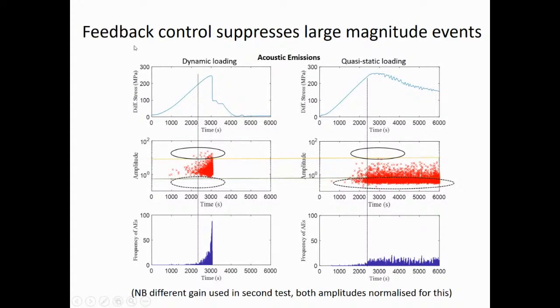Another thing we noticed about feedback control is that it suppresses the large magnitude events. So here's the dynamic loading experiment, the one that's normally done. Here's the one with feedback control, which gives us this quasi-static strain softening. The dynamic experiment gives us a lot more big events. Okay, so the feedback control, which kicks in about here on this vertical dashed line, is suppressing large events. There's a slight difference in the magnitude thresholds here. They're recalibrated to the same scale, but we used a higher gain on the quasi-static loading, because we did this test after the dynamic loading test. So we'd learned we could get away with a higher preamp gain.